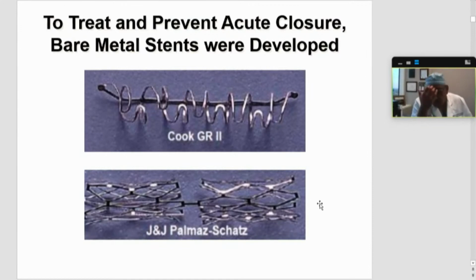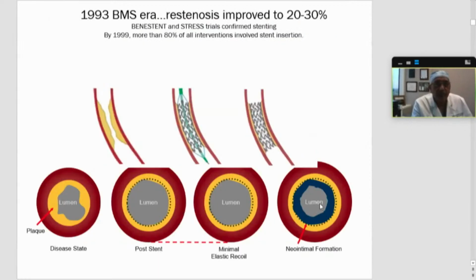These were the first two, Cook GR2 and J&J Palmaz-Schatz. And then 1993 was the BMS era. Restenosis improved, down to 20 to 30%. And there are a couple of trials, BENESTENT and STRESS, which confirmed that stenting was better than balloon angioplasty. And by 1999, almost 80% of all the interventions had a stent insertion done.